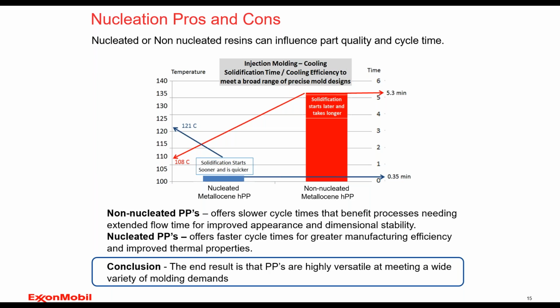And I'll just make one comment about the metallocene here. The metallocene, again, is a very narrow molecular weight and offers, in general, lower melting points. And so everything is shifted lower on that scale relative to a Ziegler-Natta type catalyst system, again, which has a melting point of about 165, where in this case, this metallocene grade has a melting point of about 158. So it's shifted lower in general. So that's one distinction that can be made here with the nucleating agent is that metallocene may need that improvement.